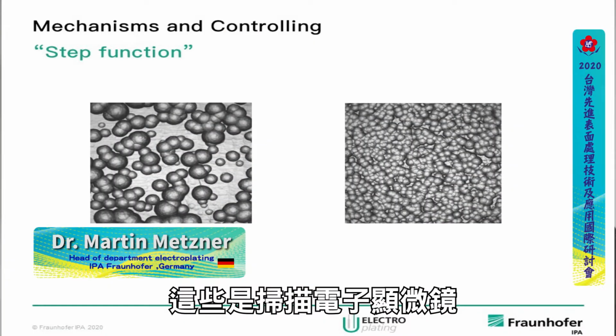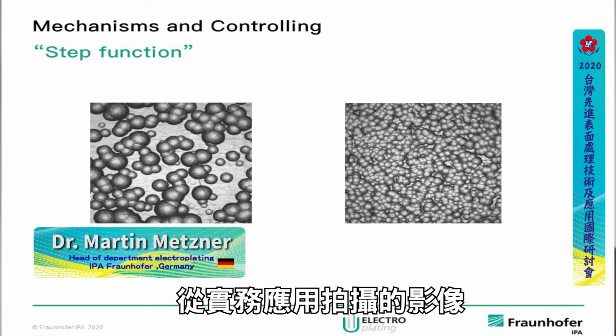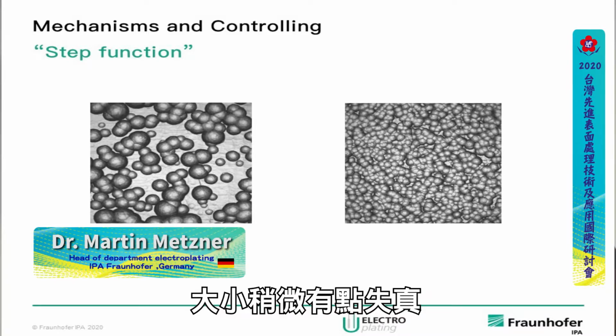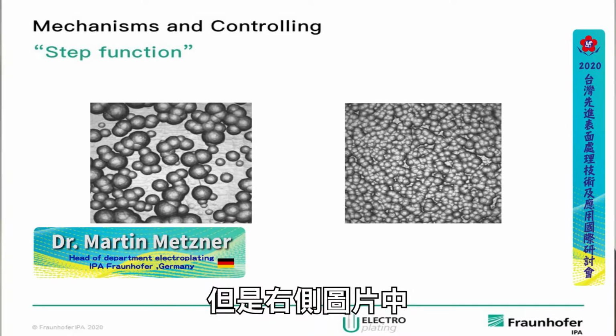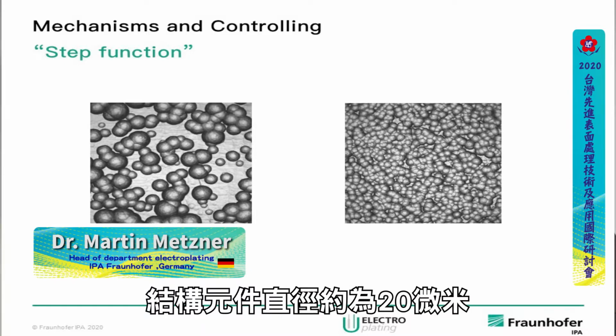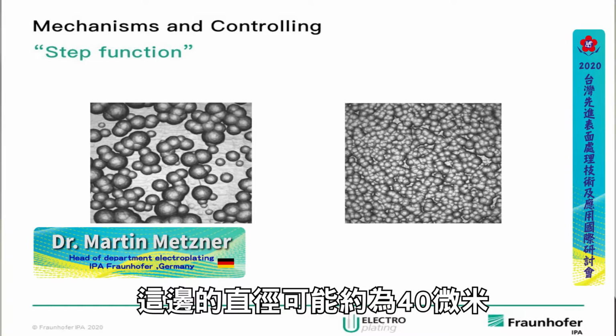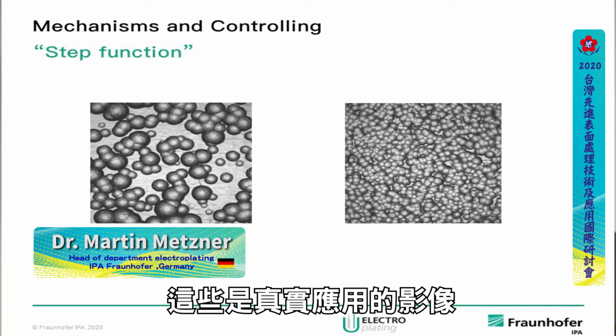This is what we learned, what we can control in our step function. And what you see here now are scanning electron microscope photographs from real application pictures. Here the size is a little bit missing, but you can say the structure elements on the right-hand picture are around 20 micrometers of diameter, and here it would be around maybe 40 microns of diameter. So these are real pictures from application.